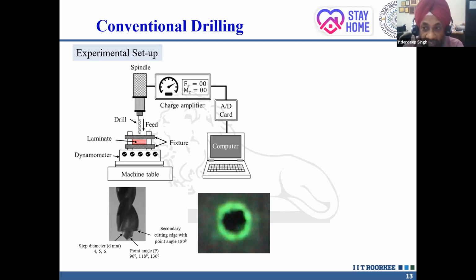The digital images were taken, and I am talking about maybe 20 years back, in 2000, 2001 or 2. We were working in this field, and then the digital images of the holes were used to quantify the damage around the hole. So we were able to read these images in digital imaging software, and then we were able to segregate the damaged area around the hole from the actual hole, and we were able to quantify.